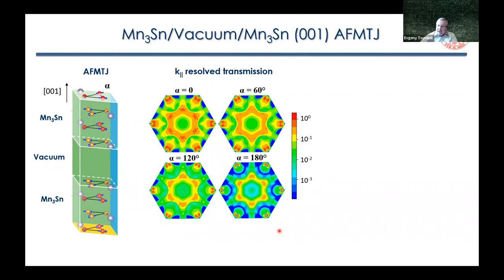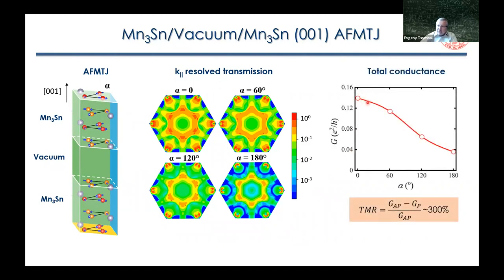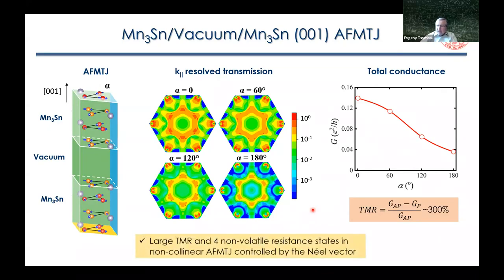If you integrate the transmission over the Brillouin zone, you find a substantial reduction in the transmission when we go from parallel to anti-parallel Néel vectors, with TMR as large as 300%. Again, it's quite a sizable number, comparable to the best magnetic tunnel junctions based on ferromagnetic metals. In addition to TMR, which relates parallel and anti-parallel configurations, all four orientations of the Néel vector are possible, because all four correspond to easy axis directions. In principle, this kind of tunnel junction may have four non-volatile resistance states, which is an additional advantage of this kind of non-collinear antiferromagnetic tunnel junction.